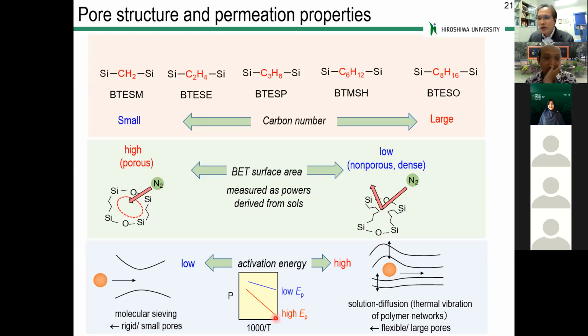In the case of the membranes, we have a low activation energy for the small linking unit and a large activation energy for the large linking unit. In the case of the small linking unit, the mechanism is based on the pore size. It is just a molecular sieving mechanism. Rigid and small pores allow the low activation energy like this, and then high carbon number is more like polymer membranes, where the activation energy is determined by thermal vibration of the network with a linking unit.